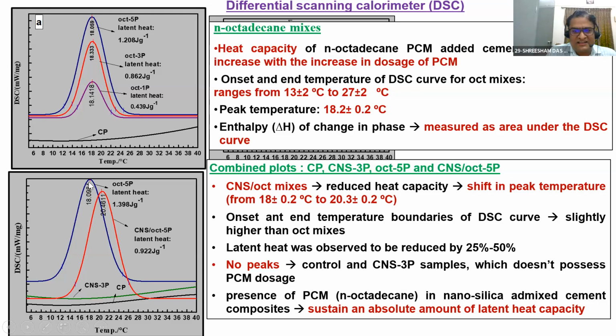What is the temperature boundary for octadecane? It is 18 plus or minus 0.2 degrees. When I'm adding nanoparticles and octadecane, that is the phase change material, there is a shift in peak temperature, that is 20.3 plus or minus 0.2. There is a small reduction in the heat capacity, but yes, I'm getting a peak, and I am able to absorb a substantial amount of heat, or a substantial amount of heat can be stored. So what have we realized? If you are going ahead with only PCM, also fine. You can absorb a sufficient amount of heat. But if you want to make your material a high performing material, that is nanoparticles plus PCM, you are also able to absorb the heat.